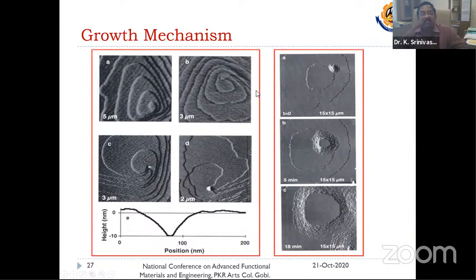This particular layer will grow. So this will rotate something like this, like moving on a staircase. So every step will be completed by the addition of growth units, and this step will propagate, and likewise a small area expands. Finally, the particular crystal surface will grow continuously, but you have to maintain the conditions accordingly to continue the growth uniformly throughout the growth period. That is a big challenge associated with any crystal growth process.